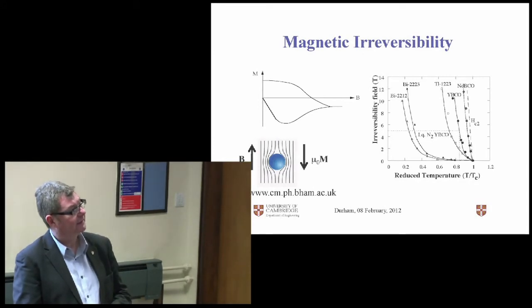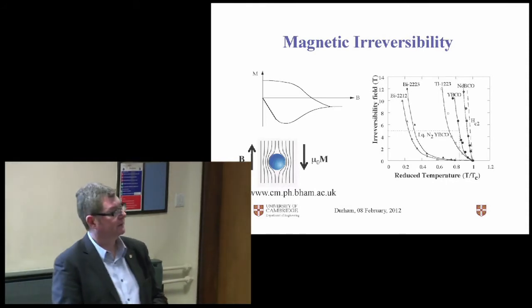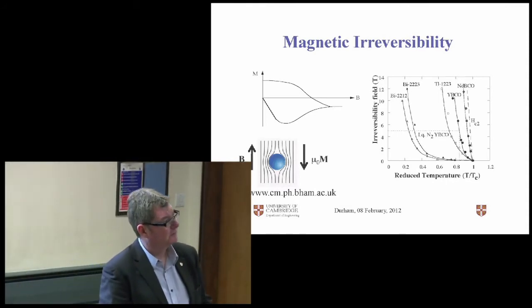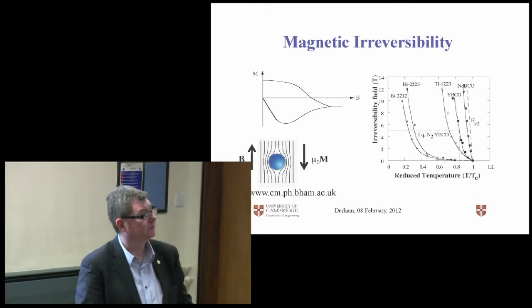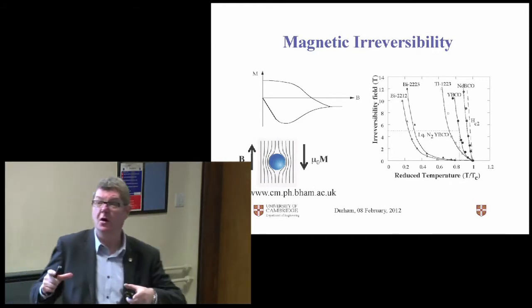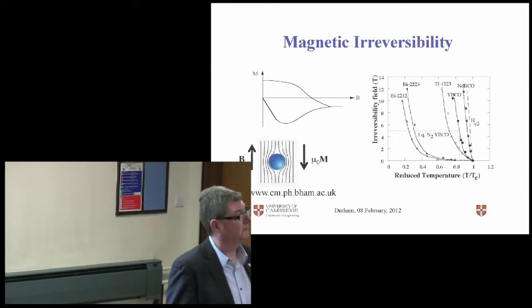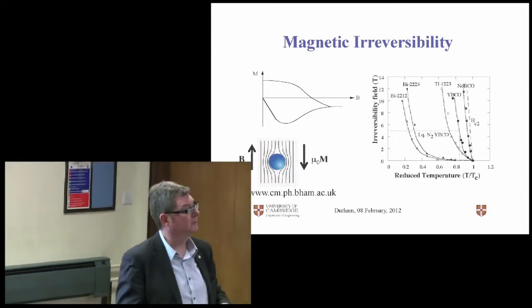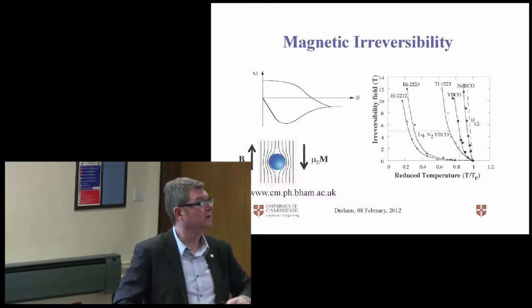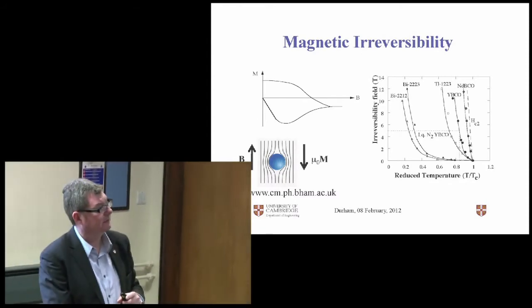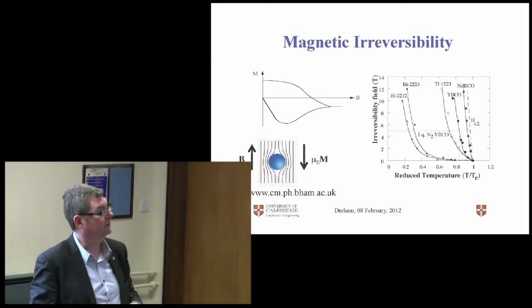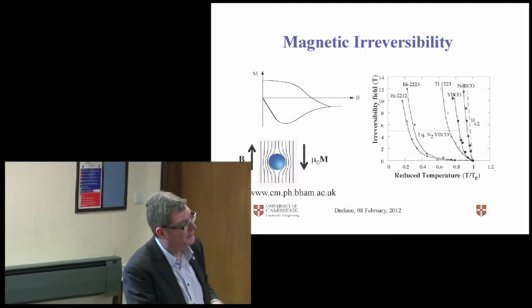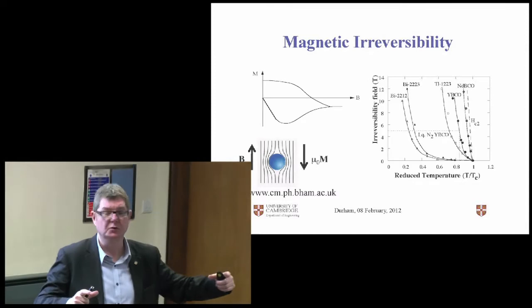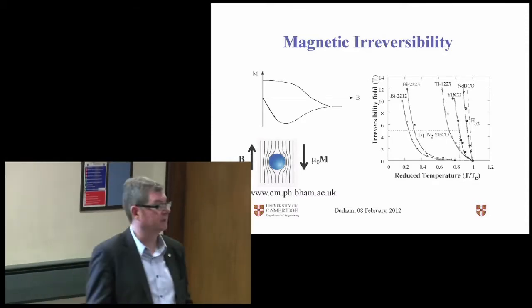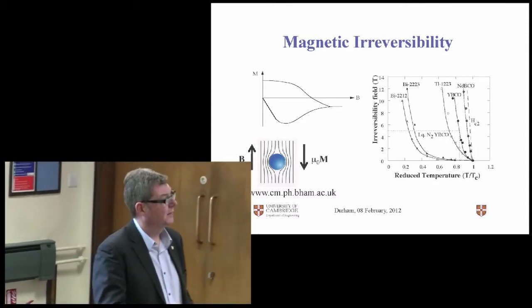We induce an eddy current, and an eddy current flows in a circle, and the magnetic moment of the eddy current is simply the product of the size of the current by the area that it defines. And if you have a bulk material that looks like a hockey puck, and these materials are often described in that way, you have nested current loops, you simply integrate the magnetic moment over the area of the sample to get the net magnetic moment. So it's a summation of all these individual current loops. So clearly, if you go to a larger diameter loop, you get a bigger magnetic moment and a bigger magnetic field. So that's what we want to do.